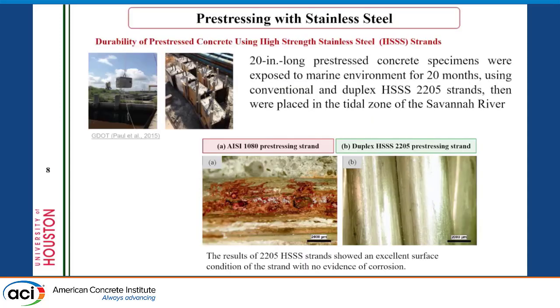Before that, I'll mention the durability of this stainless steel strand, because it's not a corrosion-free material. It's a corrosion-resistant material. In research that has been done, 20-inch long pre-stressed specimens were exposed to a marine environment for 20 months, and you could see the results: the stainless steel showed an excellent surface condition and there is no evidence of corrosion.